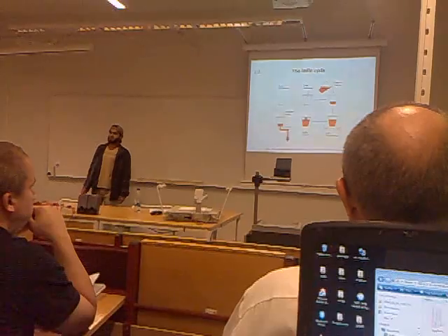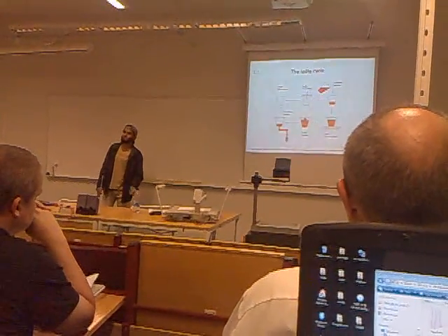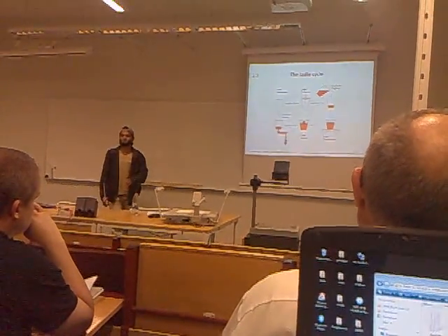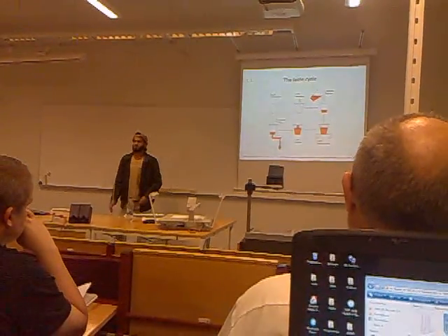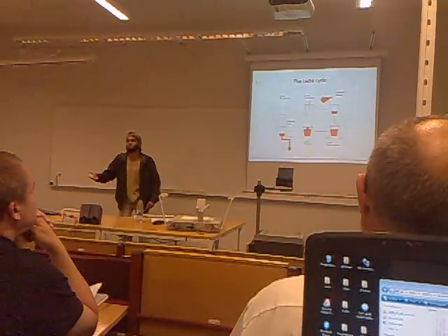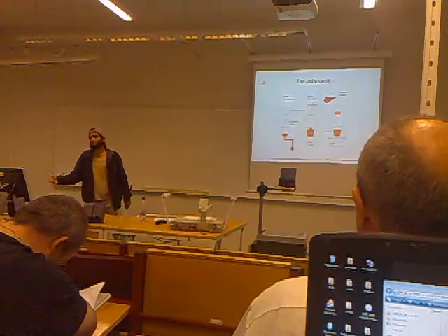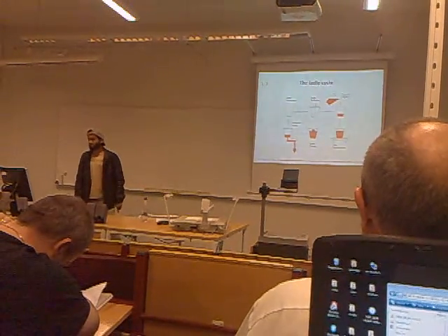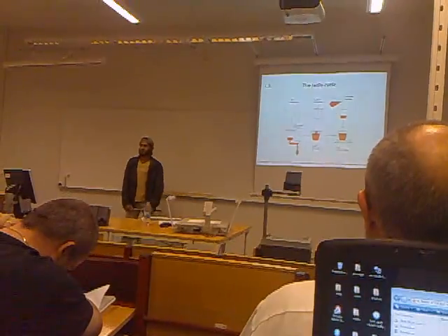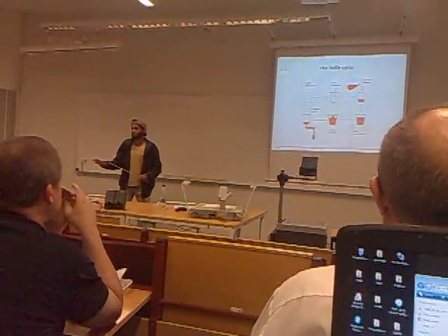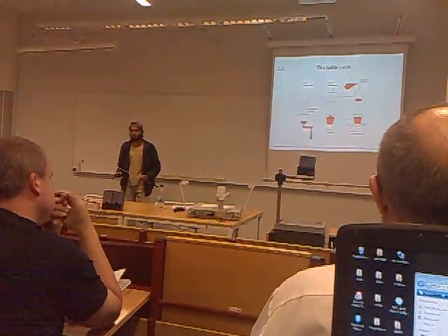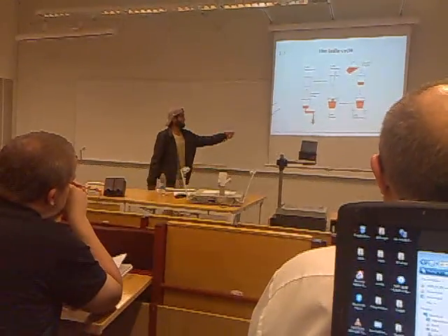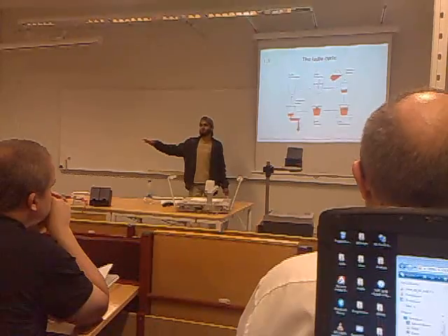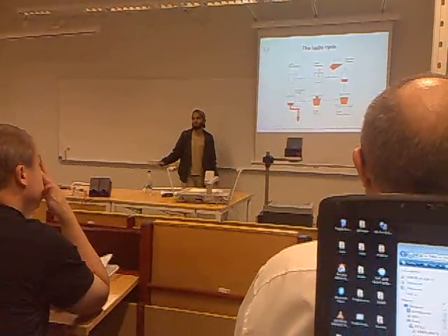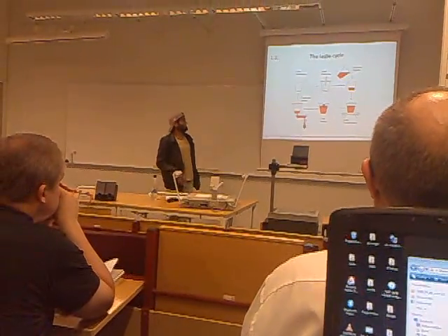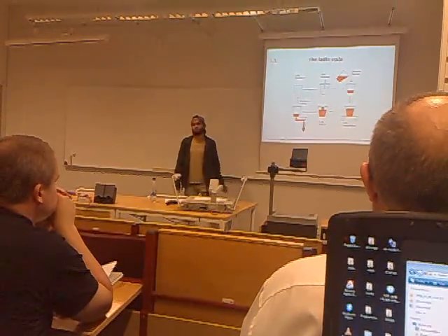The ladle needs to be at a suitable temperature for the steel to be poured into it. So if the temperature is below a certain limit, then we need to give it some heat. But if it's already at a good temperature, then we may skip the ladle preheating station and go directly to the converter tapping. At the converter tapping, at the AOD furnace, we set the initial carbon and alloy content of the molten steel, and then we tap that steel into the ladle, fill it, and then we cover the molten steel with a slag layer so that insulation is achieved from the top, and then we cover the ladle with a lid, and then it's ready for transportation.